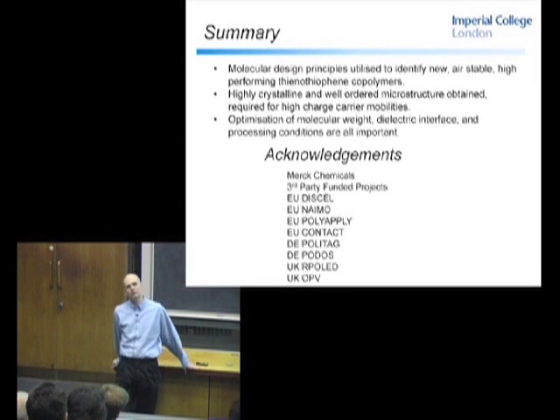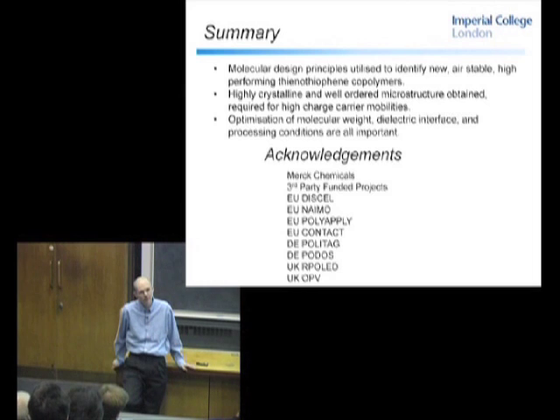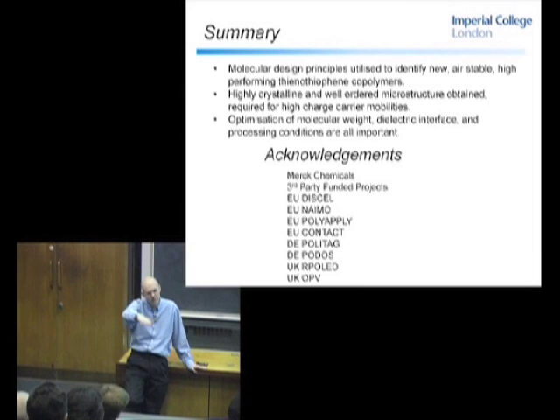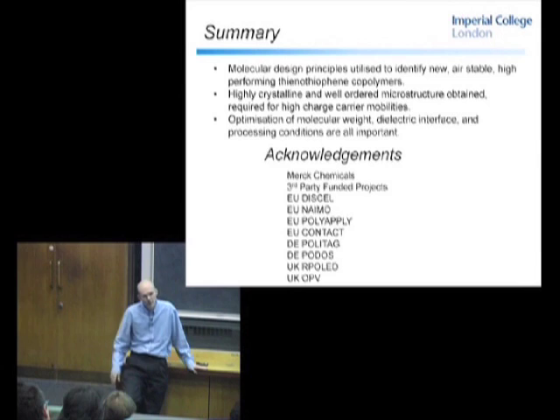There are treatments. I think there's a company in Oxford that has treatment layers for fluoropolymers. There are other solution-based treatments that Merck have been involved in. I can't talk too much about that. So there are approaches to solving that problem. You're just introducing a sort of interlayer between the Teflon-like material and the gate. There are other groups that actually don't use a solution deposition technique to deposit or print the gate, in which case they have more success putting down the gate as well. So the question remains about adhesion, delamination.